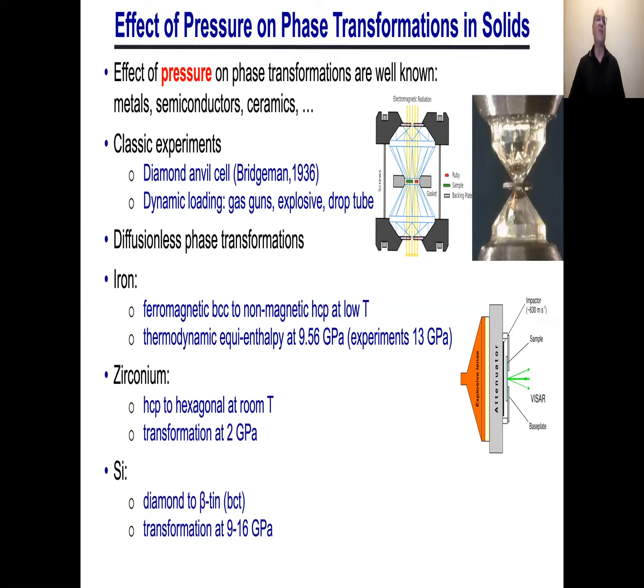Okay, so if I look at other materials, zirconium goes through a hexagonal close pack to a different hexagonal structure at room temperature at about 2 GPa. Silicon goes through a whole large range of phase transitions, including a diamond to beta tin type structure at a pressure range of 9 to 16 GPa.